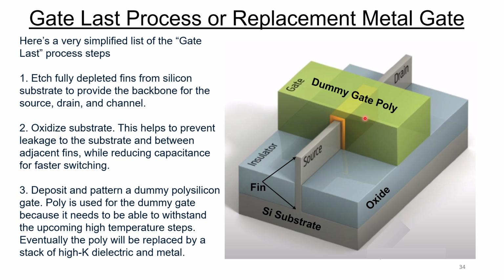The third step here is we deposit and pattern a dummy polysilicon gate, and that's what we show in green here. Now the poly is used for the dummy gate because it needs to be able to withstand the upcoming high temperature steps. And eventually this poly will be replaced by a stack of high-K dielectric and metal. The metal we're replacing the polysilicon with would not withstand the high temperature steps.